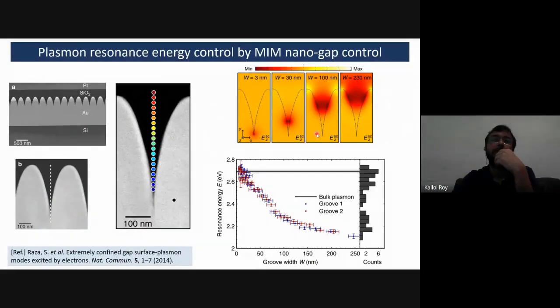Another example of such light confinement is what you can achieve at a metal interface. This graph illustrates different plasmon mode energies at different gap sizes. Previously it was a metal dielectric interface, whereas this one is a metal interface, with two metals placed at a small distance. For example, this one has a 3 nanometer gap, whereas this is 30 nanometers, and so on. You can see the effective mode energy changes as we change the gap. As we make the gap smaller, the resonance energy increases. This is another phenomenon which is a consequence of light matter interaction at smaller gaps.